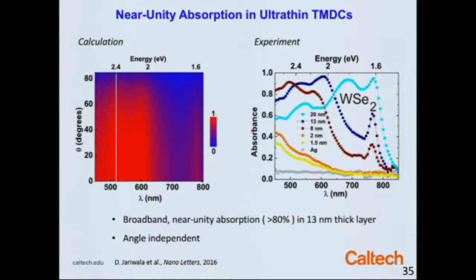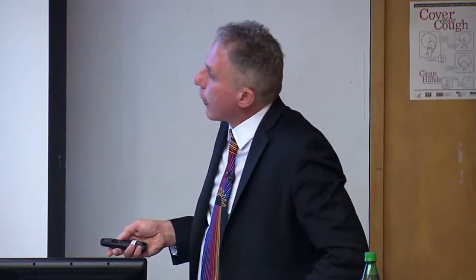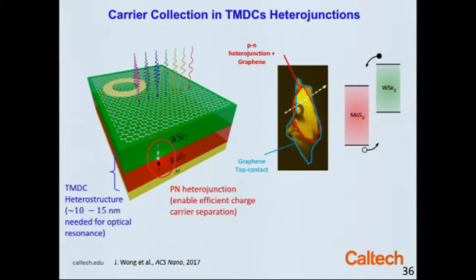And this is also angle independent. If I now look at the spectrum as a function of angle, you can see if I had some structure like a diffraction grating, it would be very, very angle insensitive. I can go to an angle of 60 degrees, and then finally I'm just losing due to the cosine losses in absorption. So it's very angle insensitive, this absorption enhancement.